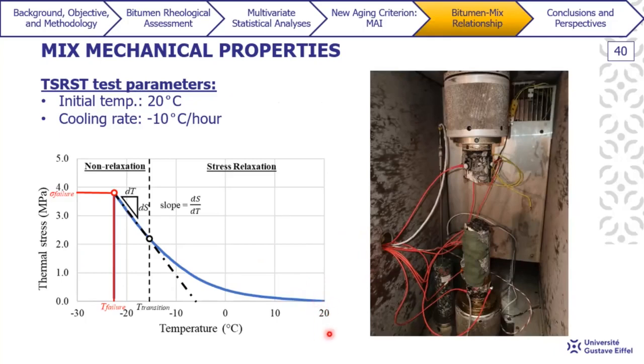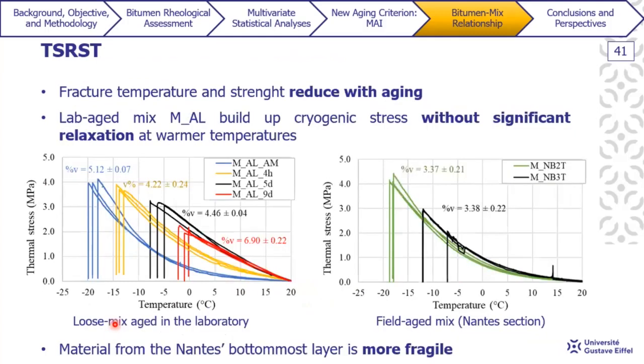Our initial temperature test starts at 20 degrees Celsius, and then the cooling rate is 10 degrees Celsius per hour. So as the temperature drops down, there will be this cryogenic stress. These specimens will experience it, and it will be registered during the test until our specimen breaks. Then we get the failure strength and the failure temperature here. Those are the values that we will be using in this presentation.